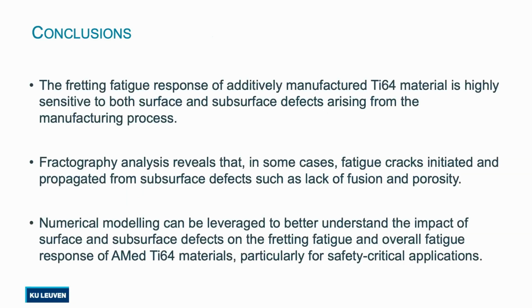So the takeaway message is that for additively manufactured material, a lot of data on fatigue of these materials are available, but we have to test it in the real condition. Definitely fractography will help us to understand the root cause, and then my finite element model will help us to understand the effect of these defects on the fretting fatigue behavior of AM material.